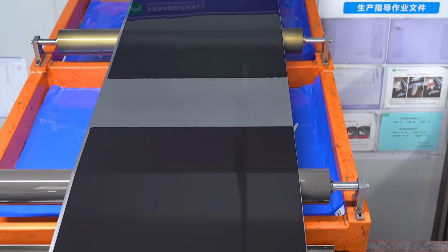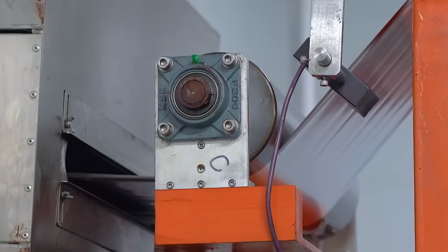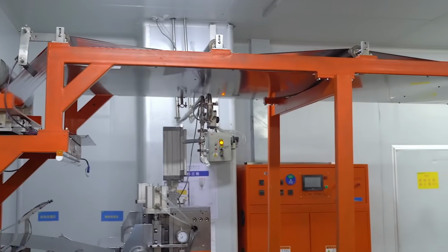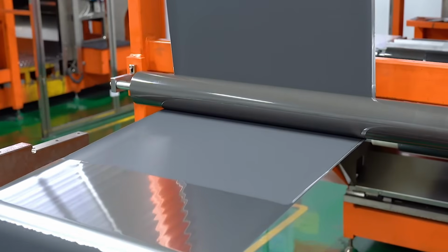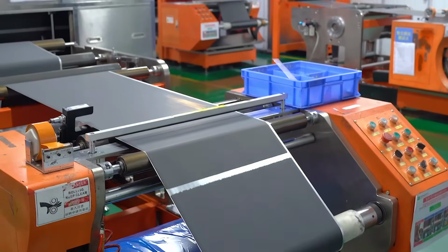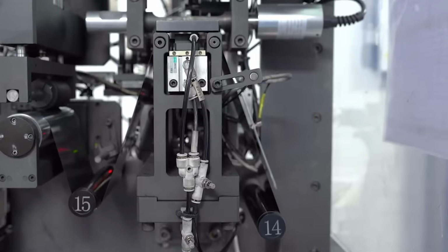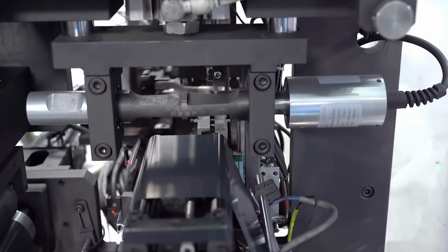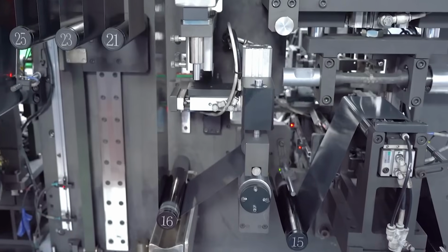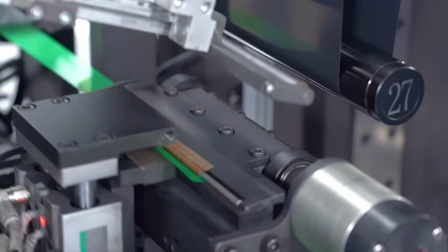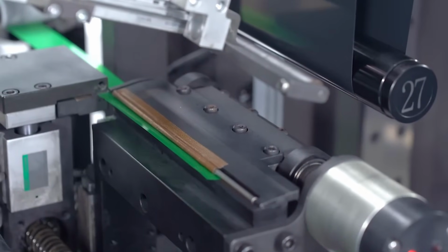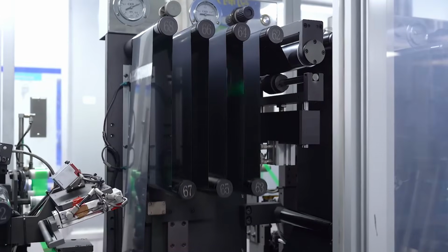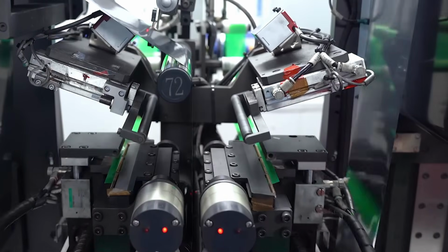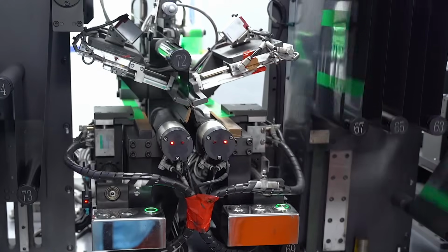Cell assembly happens in dry rooms. This is one of the least visible but most important parts of the whole process. Lithium is extremely sensitive to moisture. Any water vapor present during assembly reacts with the electrolyte and degrades the cell before it ever gets used. Dry rooms maintain humidity levels so low that the air inside is drier than the driest desert on Earth. Building and running dry rooms at scale is expensive, and getting the equipment costs down required the same kind of volume-driven learning curve that affected every other part of the process.